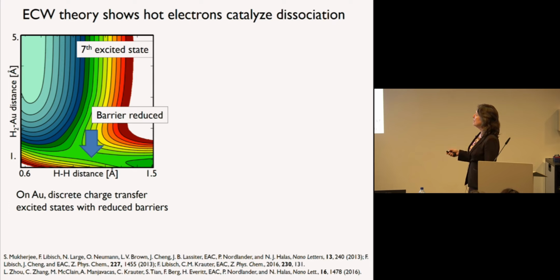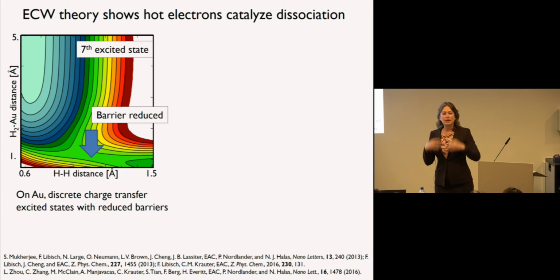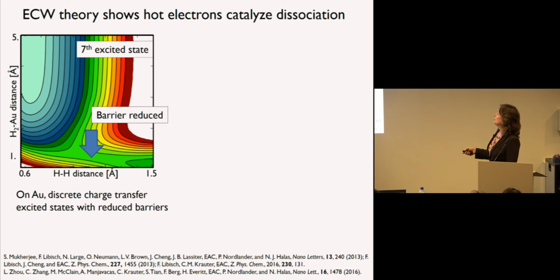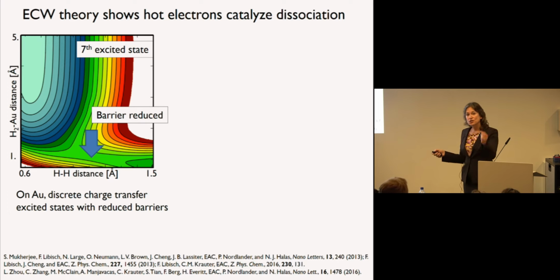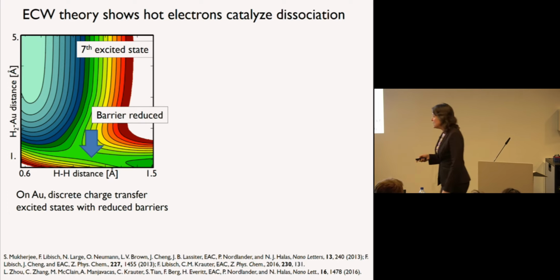So this is a 2D cut through a many-dimensional potential energy surface showing this is the H2 gold distance. So out here, the H2 is above the gold surface, comes in, and then the bond starts to stretch. This is the HH distance, and this is showing you where the saddle point is. These are individual calculations of using embedded correlated wave function theory. And what we see is that in this particular case, you do get charge transfer that occurs as you reach the saddle point. Charge transfer excited states with reduced barriers.